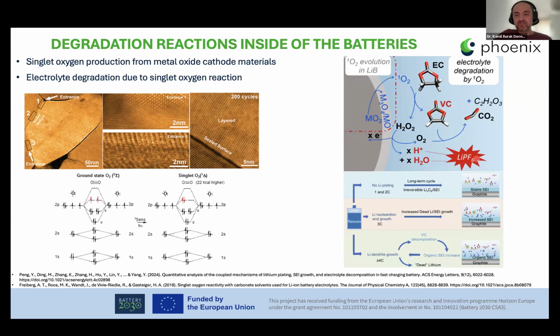Actually, water and oxygen are the most important and most disastrous components in the battery formulation during operation, because, as said, they decompose the lithium salt, leading to a huge capacity fade because of the reduction in electrolyte conductivity, and also excessive CEI formation. There is one study, a computational study of course, which shows that oxygen release is favored from the metal oxide cathode material, so it should be avoided during the operation.